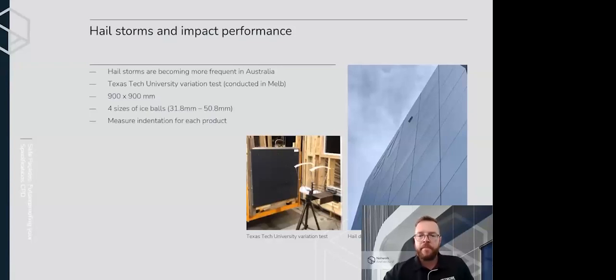Testing was conducted in accordance with the test procedures of the Texas Tech University Variation for Wall Materials for impact resistance testing of rigid roofing materials by impacting with freezer ice balls. Testing was required on an observe and report basis with measurement of indentation due to the impacts. The client, which was us, required that the sample panel be impacted at a nominal speed of 32.1 meters per second with ice balls of 4 different sizes, and then to measure the indentation for each product.